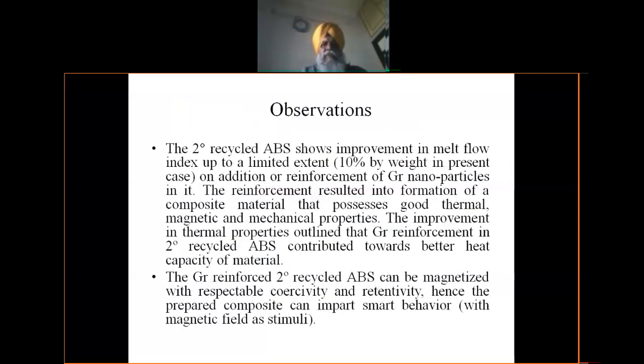Then similar to the previous case, I can go for the magnetic properties. This test is basically performed on the VSM. You can see with the different compositions of the graphene, 2.5%, 5%, 7.5%, 10%, 15%, I can see what is the effect on coercivity, retentivity, and magnetization. Basically, with the increase in the graphene, you can well see directly the magnetic properties increasing. But sometimes I have to trade off between the required magnetic property in my material, because I need to generate some electromagnetic waves, but I need to also see what sort of thermal stability my material requires. So I can do this type of balance as a material processing engineer for the development of my own material, right? So this is one observation.